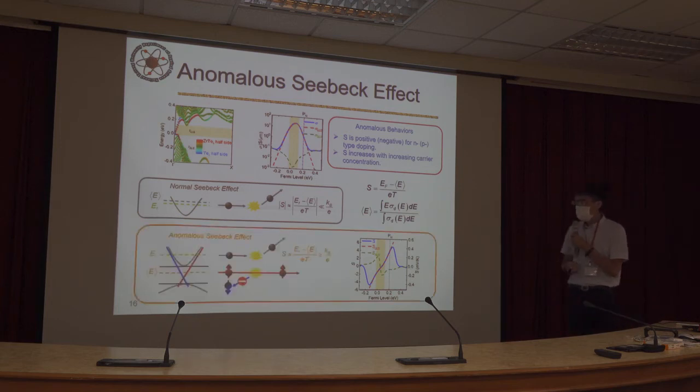For the topological-insulator nanostructures, the story can be very different. Even though the Fermi level lies above the conduction band edge, because the in-gap electrons are nearly scattering free, the average energy of differential conductivity can be lower than the conduction band edge, leading to a large separation from the Fermi level and hence a large magnitude of Seebeck coefficient with a positive sign.